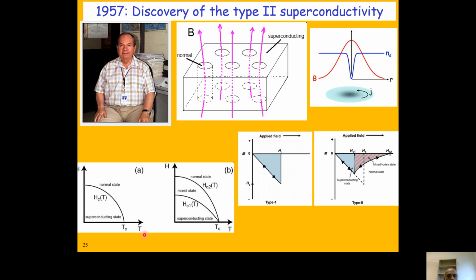If you look at H versus T, for type 1, if everything is superconducting, you have this curve, and at TC it becomes normal. But in the case of type 2, because of these vortex states, here it becomes the critical field, but it still has some superconductivity because of this mixed state, because you have these vortex states. Above this second HC2, it becomes completely normal state. That's the difference between type 1 and type 2.